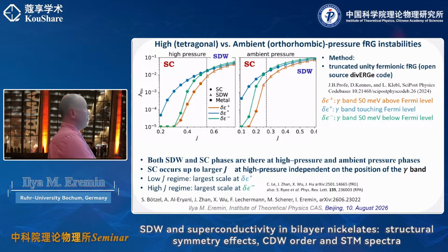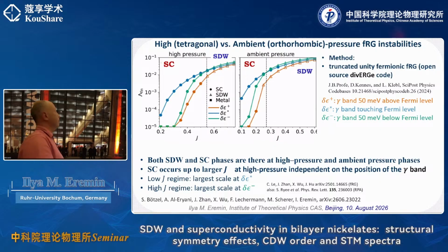When you have a gamma band which touches the Fermi level, it actually turns out to be the ideal situation for superconductivity. The system really wants to become superconducting in this case. And it's actually independent whether you're at ambient pressure or at a high pressure. So essentially, in both cases, when the gamma pocket just touches the Fermi level, it wants to become superconducting. And if you now go to the gamma band below 50 meV, below the Fermi level, then it actually favors the spin density wave state, right? And that is again something that has been well understood.